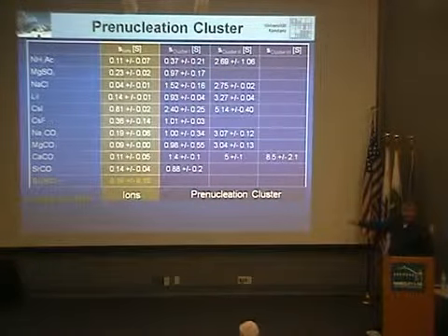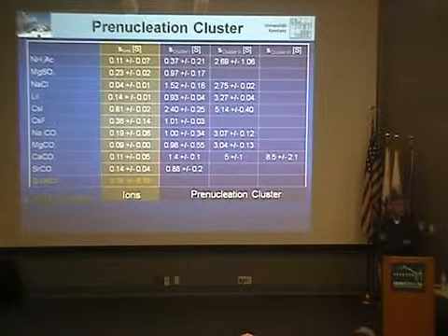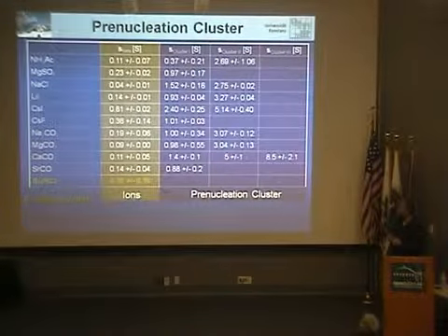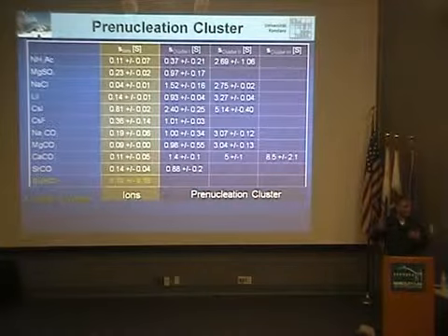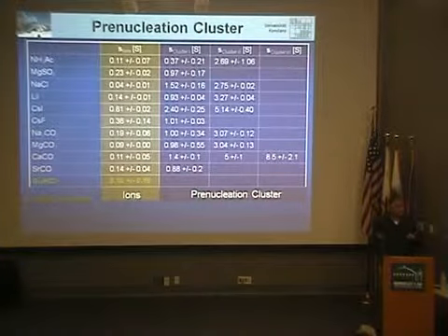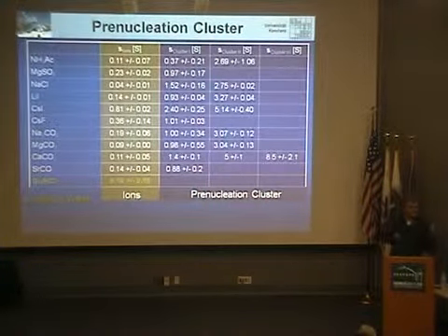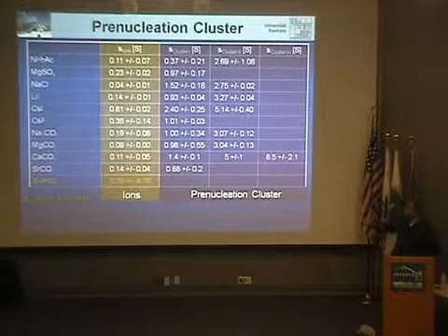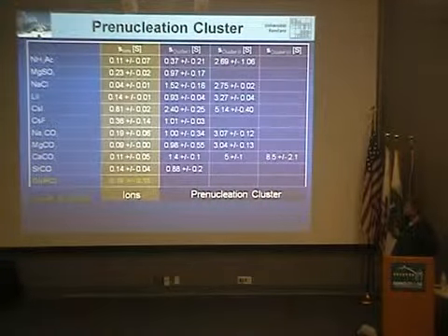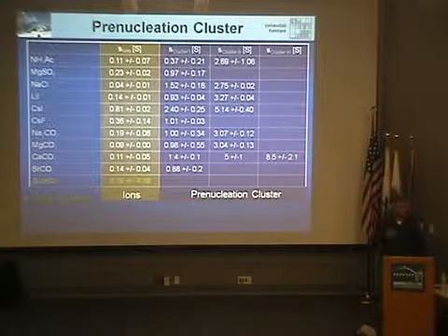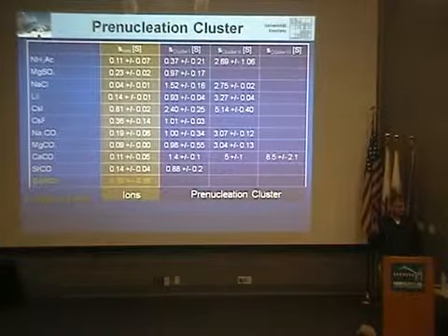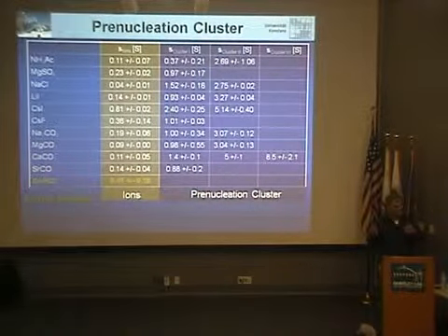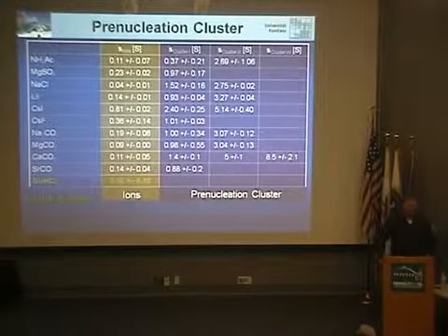Likely not. If you look at sodium chloride, for example, that's a well-soluble system, and I think it dissolves better with higher temperature, so it's the opposite of calcium carbonate, and it also forms the clusters. I think the same is true about ammonium acetate. So it seems to be more general. It's not peculiar about carbonates, which surprises us a lot. So we expected something different. We thought it's not forming for sodium chloride, but it did.